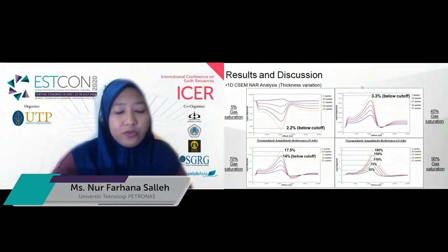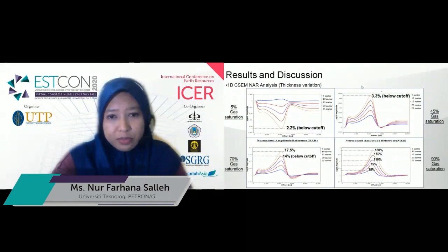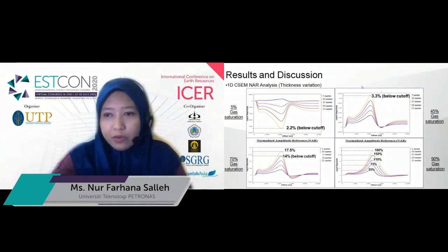This is the result for our thickness variations. From the upper graph, for 5% gas, even with 25 meters, the response is very weak, which is around 2.2% increase. And for 45% gas, the maximum thickness, which is 25, only shows a response increase around 3.3%.